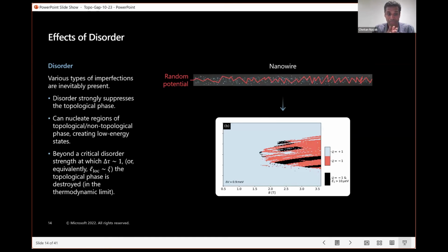completely gone. Okay, that occurs at a critical disorder strength, which is when delta, which is the ideal clean system gap, times tau, is of order 1, or equivalently, when the localization length in the wire is equal to the ideal clean system coherence length. Okay, so disorder is the enemy in this sense, and even before disorder destroys the topological phase, it breaks this big topological parabola into these smaller fragments.